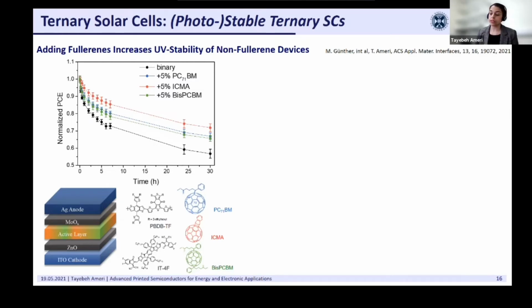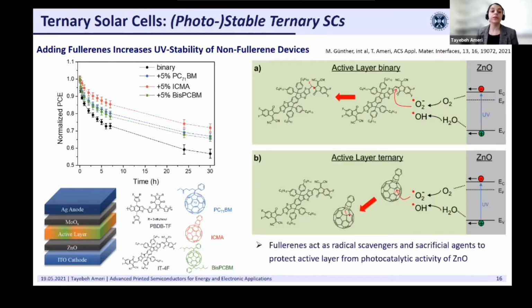Our comprehensive study showed that what is happening is that zinc oxide, the electron transport layer, which is one of the most used electron transporting layers in OPVs and also very well known for its photocatalytic activities, is inducing some radicals in the photoactive layer. Those radicals can attack the vinyl bond of the non-fullerene IT4F and damage it and degrade the system very fast, especially under UV radiation. So when we add any of those fullerene derivatives, especially ICMA, they act as radical scavengers and sacrificial agents to protect the photoactive layer from the photocatalytic activity of zinc oxide. And in this way, they can have a significant influence on the stability of our devices.